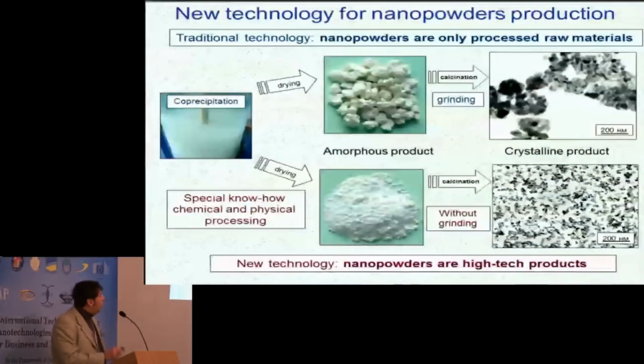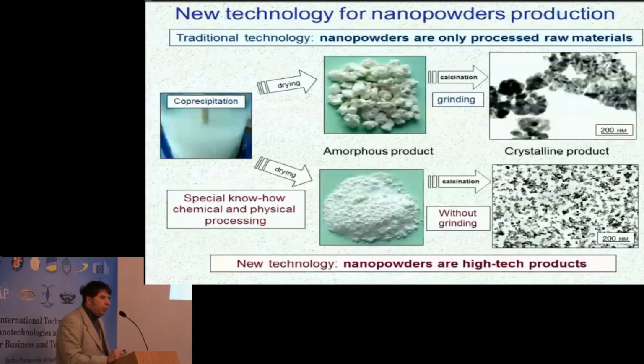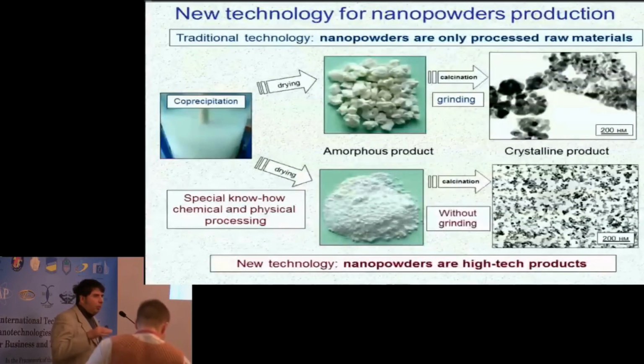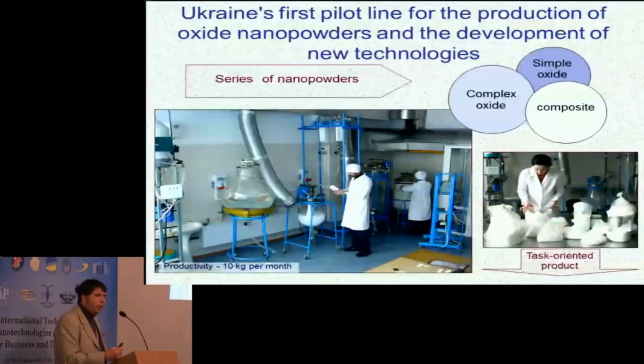Yes, it depends. Conventionally used steel is ShKh15, and we found that it's not very good for nanocomposites. It's better to use nanocomposite. It has much more stable properties. It's distance, but more correct would be to write the wear rate. The wear rate of nanocomposite paired with nanocomposite is equal to 0 after some distance of preliminary sliding. And this material can work 2 or 3 times longer than conventional coarse-grain ceramics, for example ceramics and steel. Yes. Thanks. Another questions? Thank you very much.